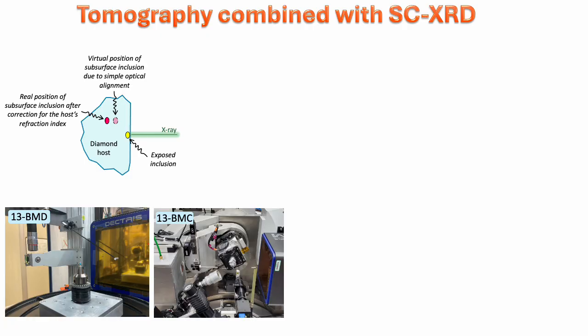Recently at sector 13 BM-D station, we have developed quite a unique combination of the tomography and single crystal X-ray diffraction technique. As you can see here, we can do X-ray diffraction from the sample, and also we can run the tomography setup. And at BM-C, we can do radial diffraction of the sample. It's important when we want to study inclusions in the material, like diamond inclusions.